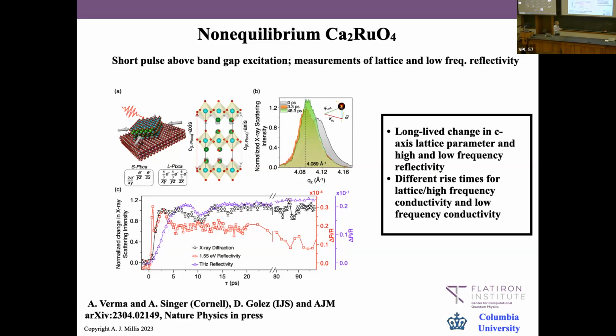If you excite it above a certain threshold, then three things happen. Well, first, this red curve, which is a plot of things versus time, just shows that the excitation that you made does something essentially immediately. This is the reflectivity at essentially the band edge.